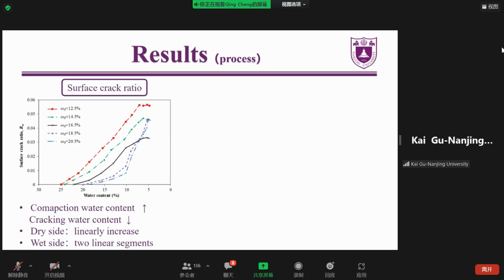This is because for these samples, all the cracks initiate at the same time and the generated cracks gradually widen with further drying. However, it is different for the soil samples compacted on the wet side with unimodal pore size distributions. The relationship between the surface crack ratio and the water content can be regarded as two approximately linear segments, right? The changing rate of the first segment is much smaller than the second one.